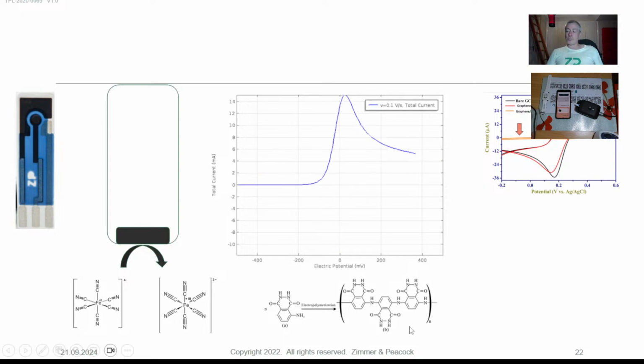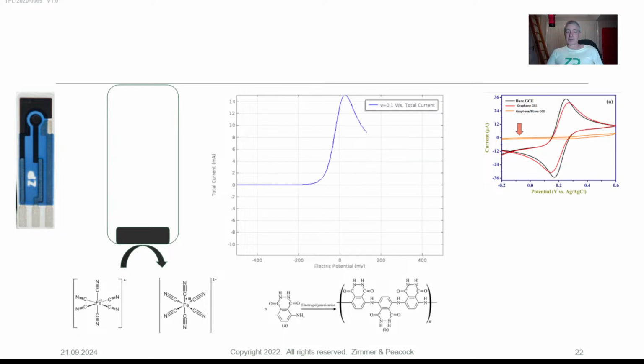It's a very organic compound, which probably means that it doesn't necessarily want to do a one electron exchange with ferrocyanide. It probably prefers to do maybe 2 electron exchanges. I should say it's not super surprising, but I'm talking about hindsight. Hindsight's a great thing, but I can be very clear here that it's no criticism of you, but you do not see it, because in fact your own data tells you that the charge transfer resistance between ferrocyanide and polyluminol is very high.